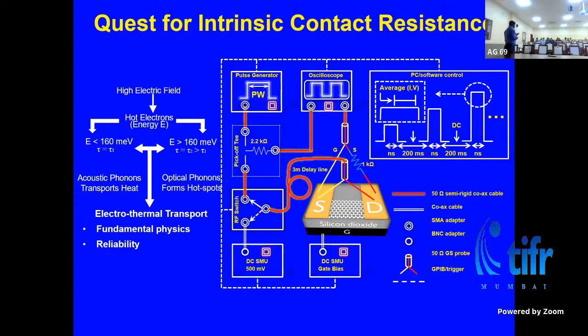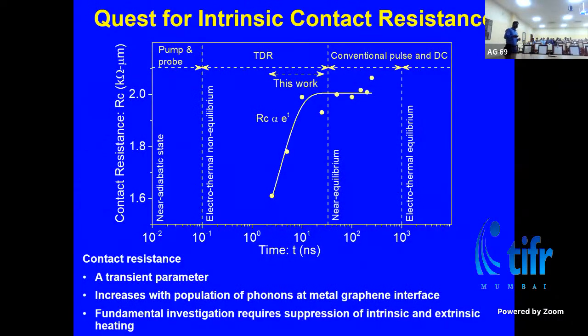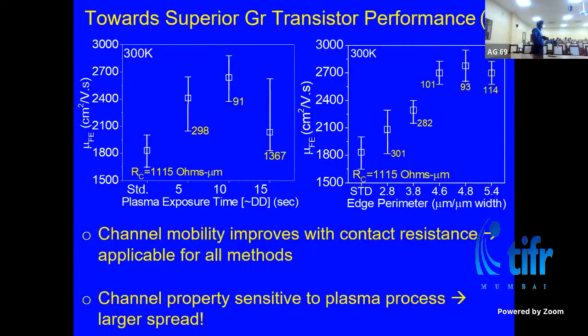So how do we get rid of that? For that, we try measuring things at much shorter time scales. So we went down to 2 nanoseconds. And what we found is that whatever you measure at room temperature, this contact resistance drops further when you go to these short time scales. So now the intrinsic contact resistance is measured not only at low temperature but also at lower time scale. That's what we figured out and published in that APL paper. Now coming back to this thread. As the contact resistance went down, the mobility also improved, and that's what I was talking about. And even if we had removed the effect of contact, we know that the mobility would have still improved because we have seen that directly in the transistor characteristic.